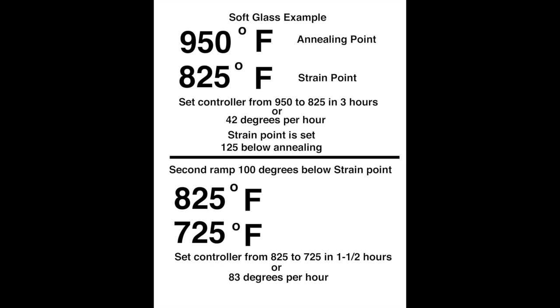But with soft glass, you need a second step. And so we're going to go another 100 degrees from 825 to 725. And at this ramp, we're going to actually speed it up. So we're only going to use an hour and a half, or approximately 83 degrees per hour, and that'll give you an hour and a half ramp down time. Now, depending on the oven that you have, in most cases, getting down into the 700s, you can usually just turn the oven off, and that would be safe enough.